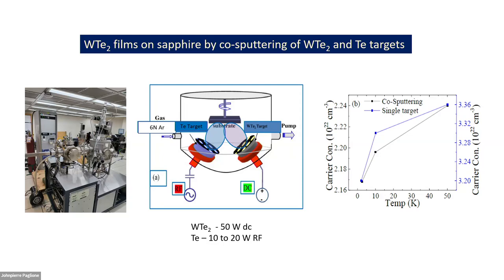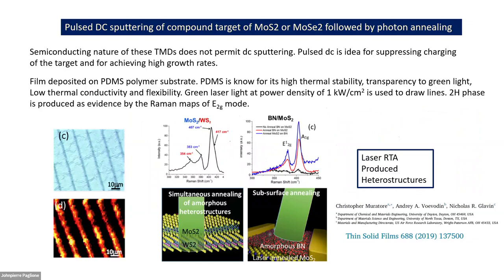And you can see from here, if you measure the carrier concentration of these films at various temperatures, you can see that the carrier concentration is very high, about 10 to the power 22 carriers per centimeter cube. A good quality tungsten telluride should not have more than 10 to the power 19 carriers per centimeter cube. So these extra carriers are coming because you have a lot of tellurium vacancy. You are literally looking at almost like a tungsten film, okay? So we gave up this, but there are people who have made good use of sputtering to make device quality